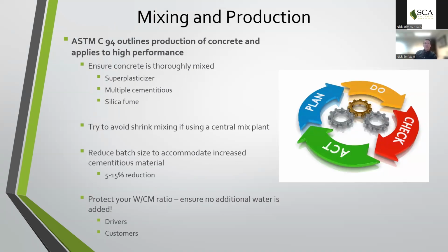Most of this process is actually outlined in C94, doing everything we can to ensure the concrete is properly mixed, especially when you have the addition of multiple cementitious materials, particularly silica fume, high levels of superplasticizer, and other more novel admixtures like we talked about, shrinkage reducing admixture, viscosity modifying admixture, admixtures that are often added at the end of the loading procedure. Ensuring well-mixed concrete can make a world of difference.